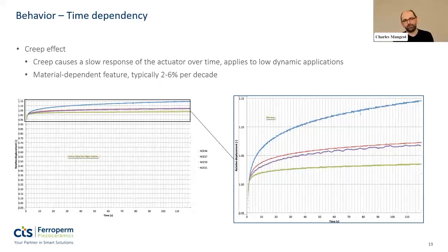There are some models where you will see the displacement or the strain expressed as a function of charge, typically with the remnant charge plus the additional charge squared, and then there's a factor. There is some research about that and some papers.